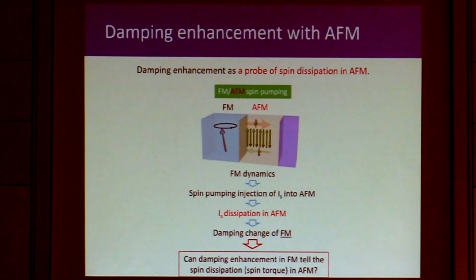So what we have done is basically just replacing this non-magnetic material with an antiferromagnetic material. Again, we excite the dynamics and pump a spin current into the antiferromagnet. If the spin current is dissipated in the antiferromagnet, a damping change should be observed in the ferromagnetic material. From there, we can say that there is a spin torque effect in the antiferromagnet.